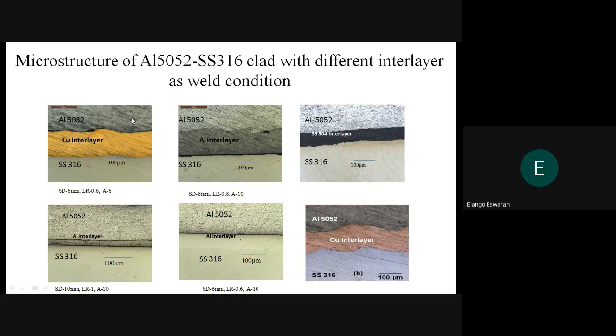So this slide shows the microstructural characteristics of the aluminum 5052 SS316 clad with different interlayers and different parameters. All the pictures show that this microstructure analysis shows the interface is devoid of intermetallic compound, trapped gas, crack and other defects. This is due to the proper selection of the process parameters for the experimentation.